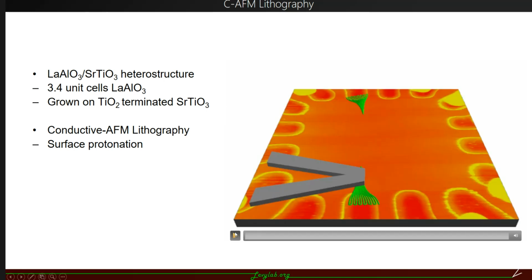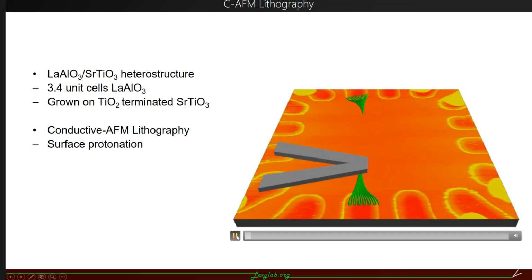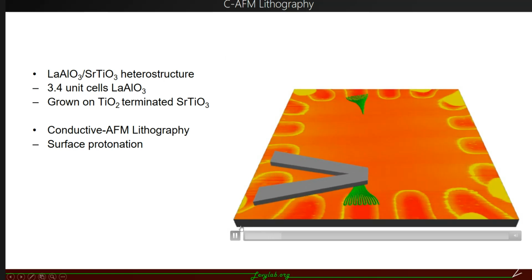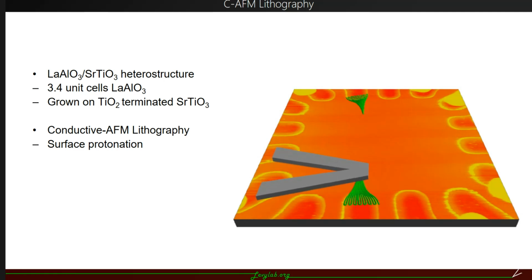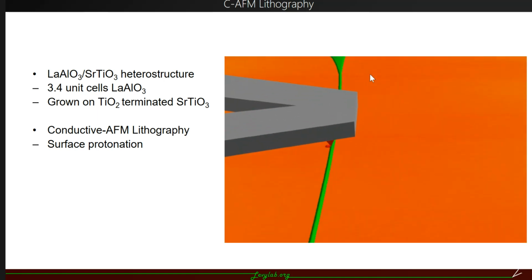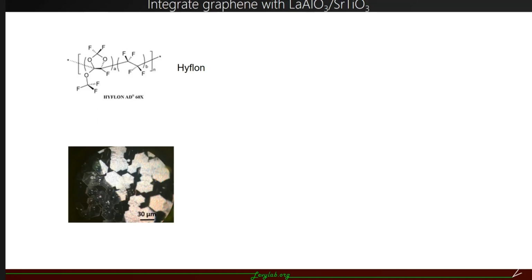So here is an animation showing how the writing and erasing process works. First, we apply positive voltage to the tip and write two triangular-shaped patterns, which we call virtual electrodes. Those help to form robust electric contact to the oxide interface. And then we apply positive voltage to draw one nanowire connecting these two virtual electrodes. Then we see a conductance jump between these two electrodes. After that, we apply negative voltage to the tip and create an insulating gap in between. So this will cut the wire. This writing and erasing process is reversible in our system.